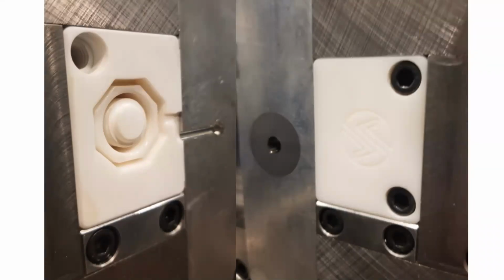So as Jake was talking about mold spray, we were rather surprised because, of course, we started the mold with mold spray, and part of the process, we want to see how it's going to behave without. We were running this the last 60 to 70 cycles without putting mold spray on at all. You would notice it when you're taking the thread core out, but the ejection itself was not a problem. One of the things we were doing to eject this part, if you look at the image on the left of the B side of the mold, we were ejecting the center thread core with a large diameter ejector pin behind that core. So when it ejected, we had the whole thread working for us, and we would demold the brim automatically, and then we would demold the thread manually.